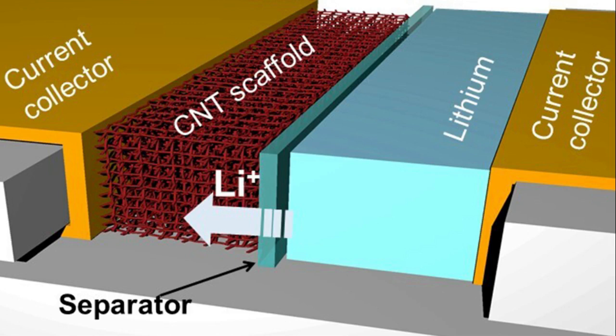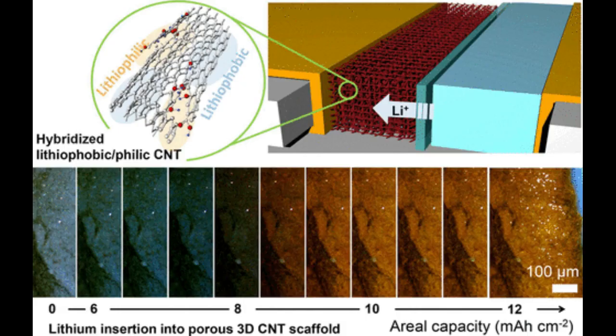However, these structures do not bind to lithium ions favorably. Hence, they made two other carbon nanotube anodes with a slightly different surface chemistry. One laced with an abundance of molecular groups that can bind to lithium ions, and another that had the same molecular groups but in a smaller quantity. With these anodes, they built batteries to test the tendency to form dendrites.